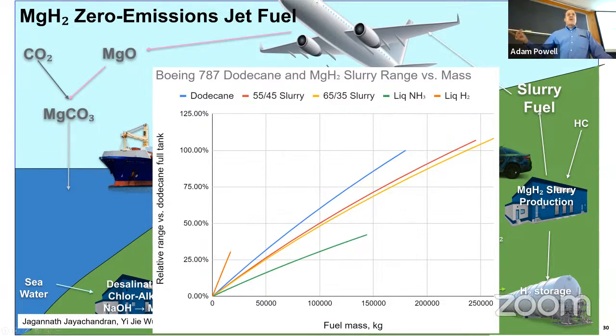Of course, you can't put those into the fuel tanks because they have to be either pressurized, which today's fuel tanks in aircraft are not, or cryogenic, and same thing. You can't. So considerably better range than either ammonia or hydrogen for aviation. Of course, the higher weight means that you'll have a heavier landing gear and wings and other structures. So probably lose that 6 to 8% better range and end up with comparable range. But there is no other proposed solution for aviation with comparable range. Lithium batteries, of course, are way down here somewhere. So they're great for a couple hundred miles, but not for your transcontinental and intercontinental flights.